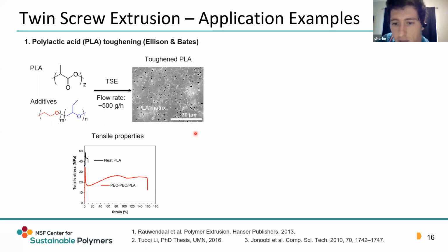In industry, a lot of times, twin screw extruder is used to make master batches in different compounds. One master batch example from the UMN is from the Ellison and Bates group, in which PLA is mixed with a block copolymer, at a production rate of about 500 grams per hour. This material is then used for film blowing experiments, and you can see from the tensile property curve that the block copolymer toughens the blends and gives the material better properties.